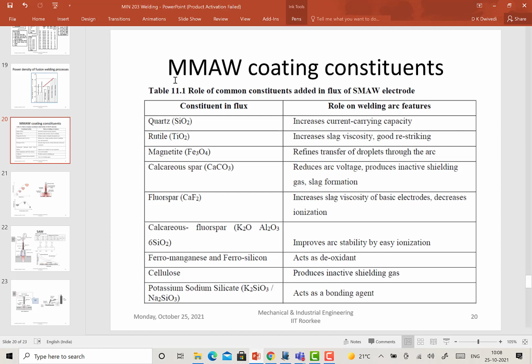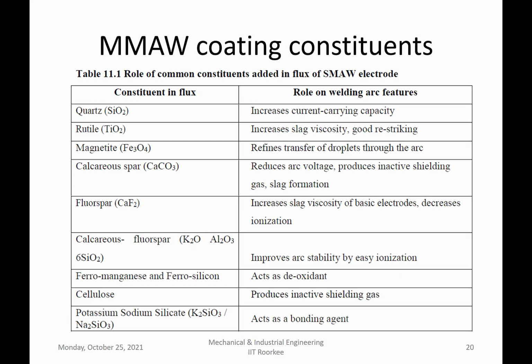So basically shielded metal arc, or SMAW, or you can say manual metal arc. In these electrodes we have coatings, which are incorporated with a variety of constituents. Quartz is one, that is silica, SiO2. Whenever it is added, it helps to improve the current carrying capacity of the electrode. Normally a 3.15 mm electrode offers a current carrying capacity of 162 to 180 ampere, but when quartz is added it may improve up to 200 or 230 ampere. Why? Because it allows the flow of current without unnecessary electrical resistance heating of the electrode itself. So that is the good part.